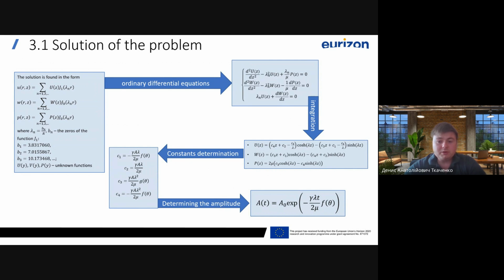To solve the problem, we apply separation of variables in the axisymmetric domain, using Bessel functions as the basis. The velocity and pressure fields are expanded into a series that automatically satisfies the boundary condition at the symmetry axis. Substituting these expressions into the governing equations reduces the system to ordinary differential equations in the vertical direction. These are then integrated, yielding closed form solutions that depend on a small set of integration constants. The constants are determined by applying boundary conditions, including the stress balance at the free surface, where surface tension acts as the driving force for leveling. The shape of the surface is expanded into a Bessel-based Fourier series, and under the small gradient assumption, the curvature simplifies accordingly.